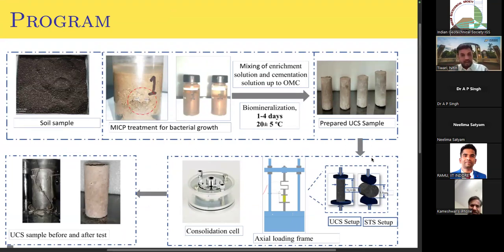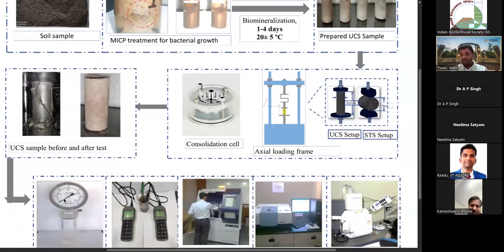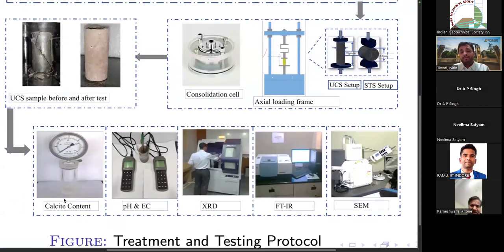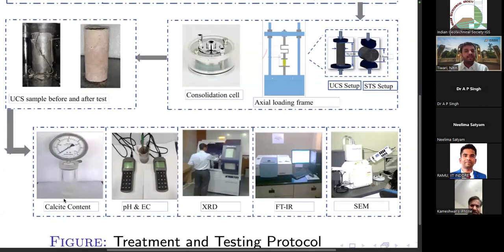And once we did this, we tested for the mechanical properties, like unconfined compressive strength or split tensile strength. We did the consolidation, and then you can see these kinds of images. I'll talk about it. I really want to talk to the students especially about these tests, because these are important tests. Generally, I have a very rich experience of 4 years of working in a private college in Bhopal, Madhya Pradesh. We generally do CBR or UCS at our labs, but we never think about how we can incorporate the microstructural effects so that we can understand the mechanism.